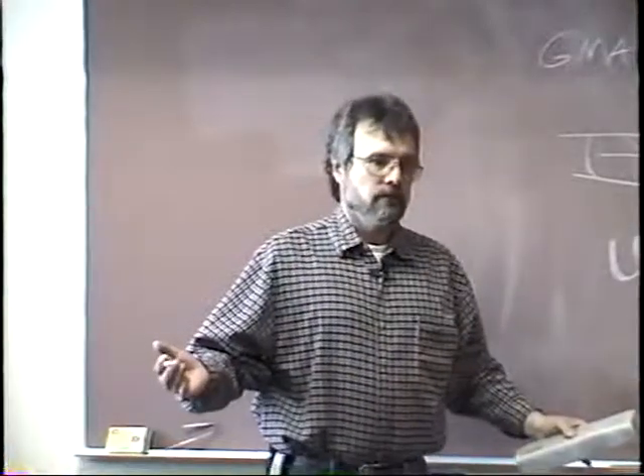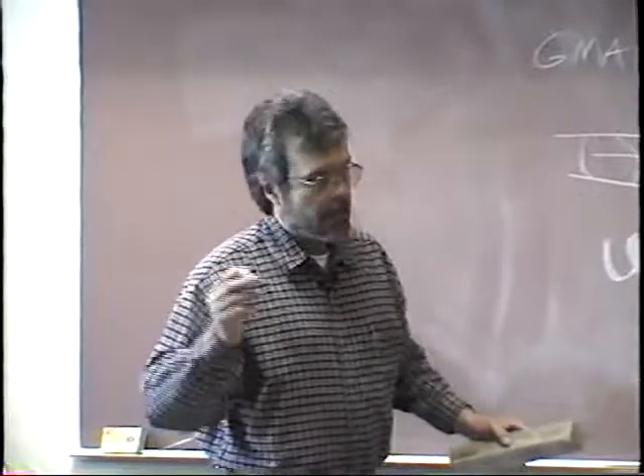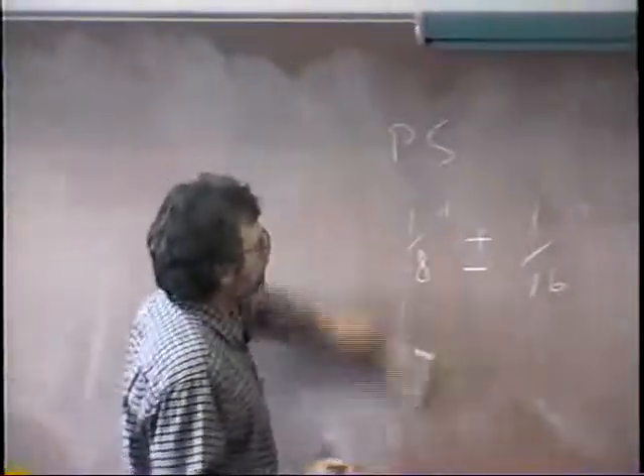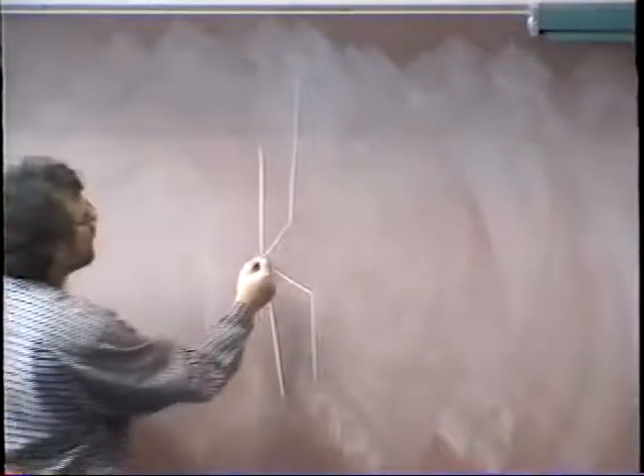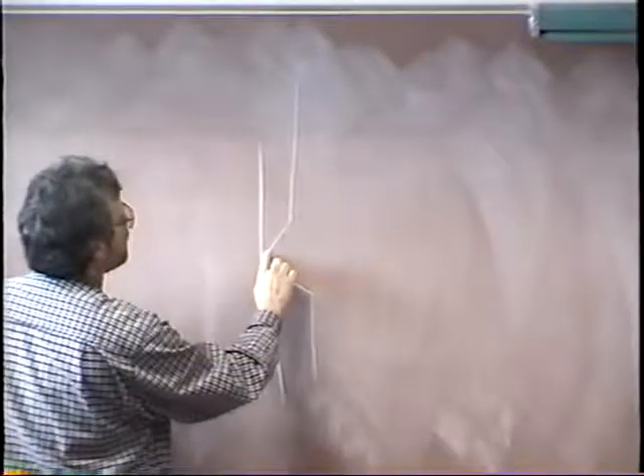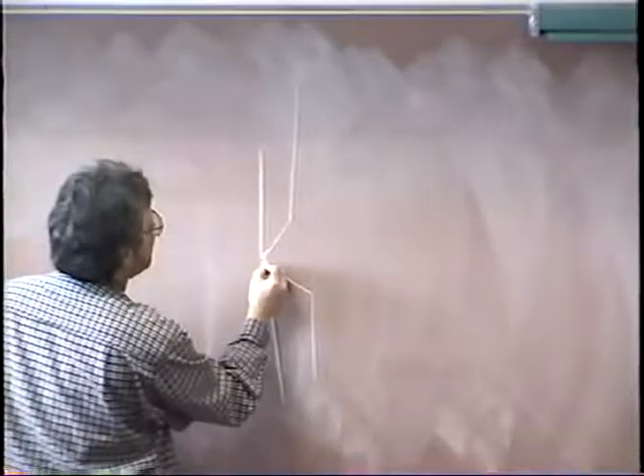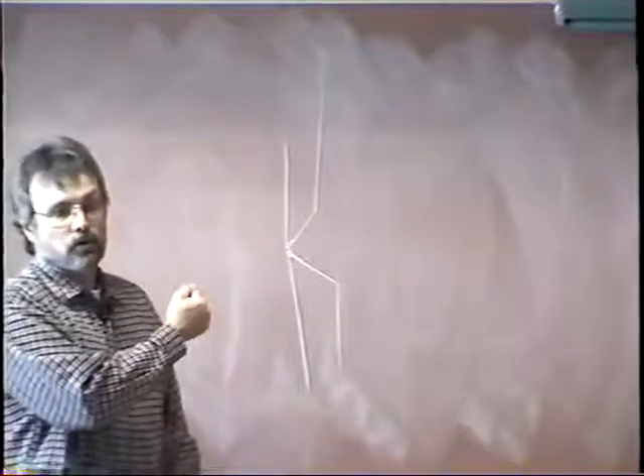So if it's too narrow, it's not going to take you long to realize it's too narrow. Stop, crank up your amperage. Another thing that you can do, and I see pipe welders, pipeliners do this a lot. If they've got it like this, and these guys only use like a 1/16 of an inch land, and it's too narrow and they're not getting through, they do what's called softening. They'll take a grinder and they'll grind right down into here and remove some of that bevel. That's what they term softening. They'll go around it with a grinder, thin that out, and then they can still use their normal welding current and blow through that. So those are a couple of techniques that you can use.